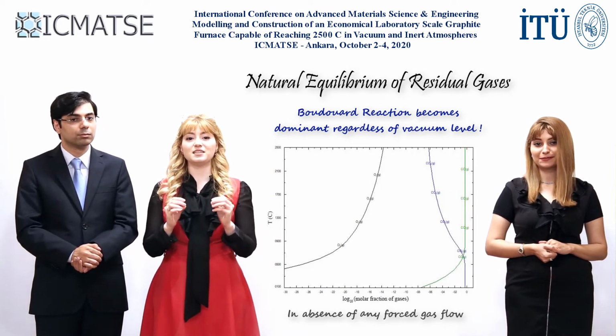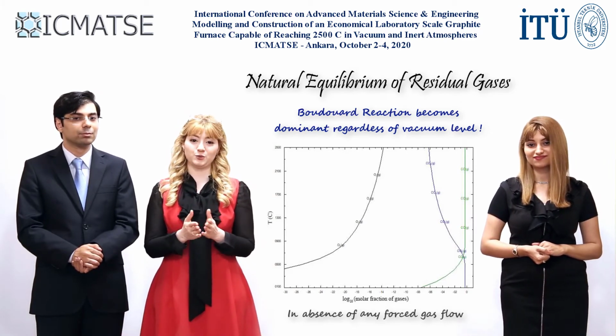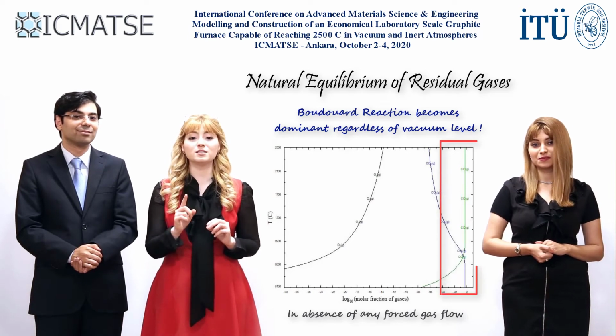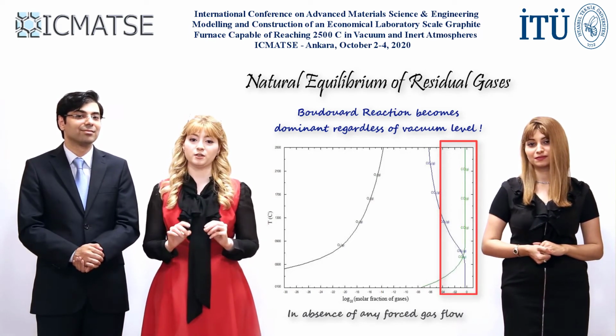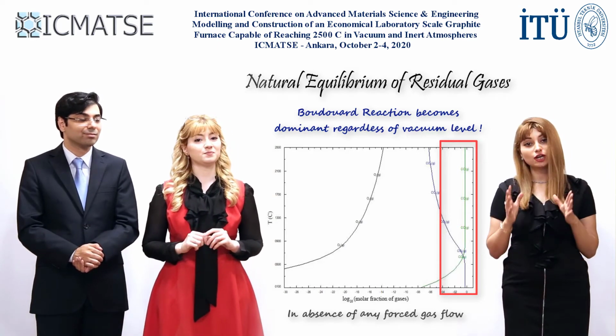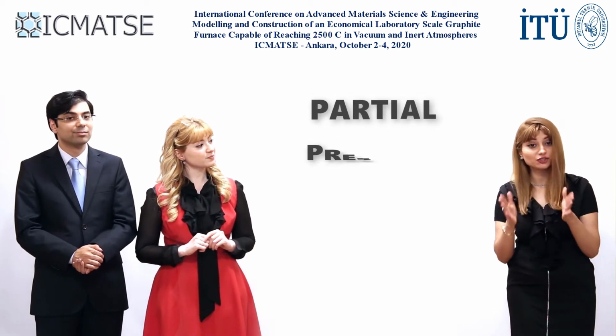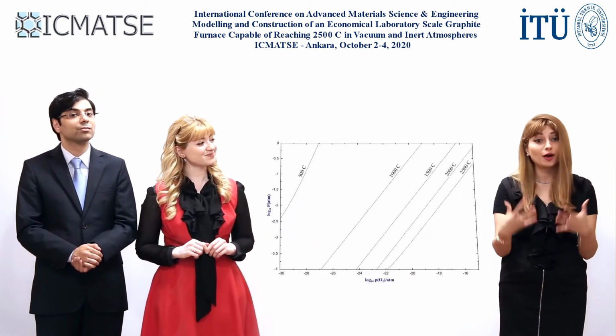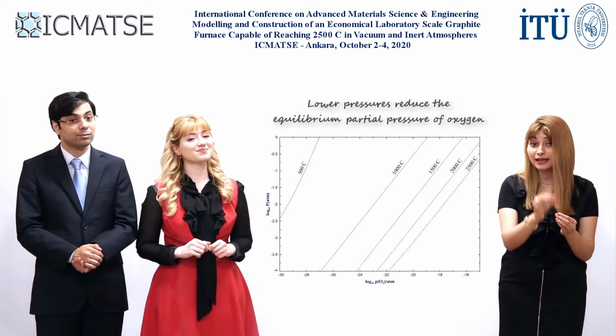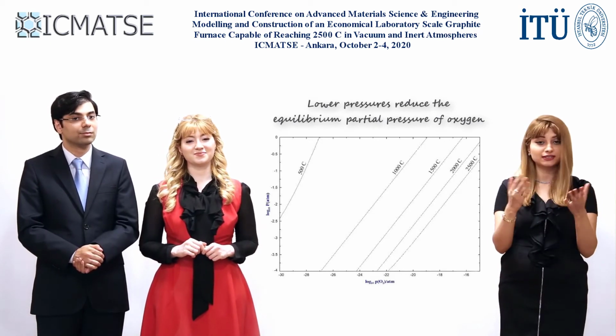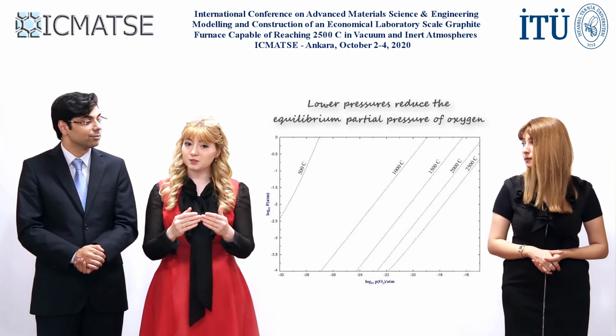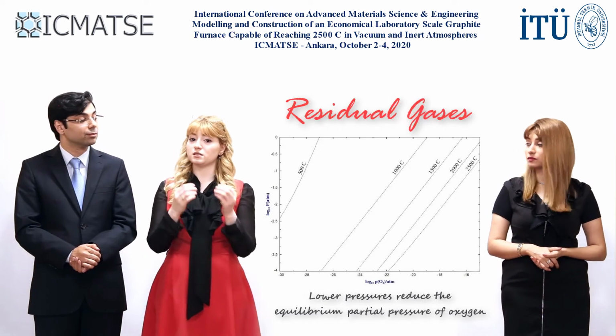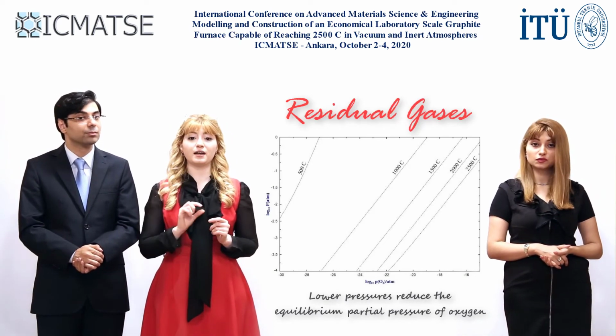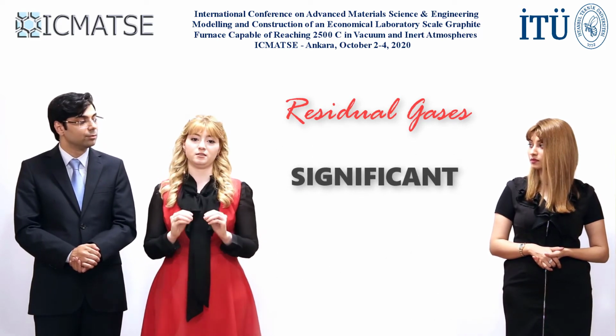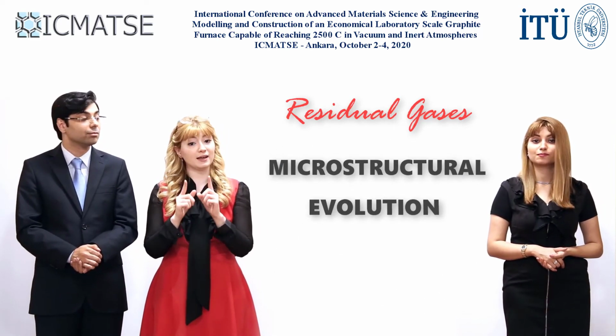The molar fraction of gases which emerge under 1 atmosphere total pressure are shown here. And it should also be noted that carbon monoxide's partial pressure cannot be ignored, regardless of the process in question. It should also be considered that the equilibrium partial pressure of oxygen in such a system is pressure dependent. Therefore, the choice of vacuum level or positive atmosphere's total pressure should be taken into account prior to experimentation with such a system. Special attention should be given to furnace atmospheres as a result of residual gases during a sintering or heat treatment operation, since this factor can have a very significant influence on microstructural evolution and defect chemistry of the material being researched.